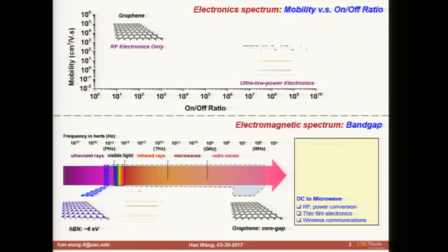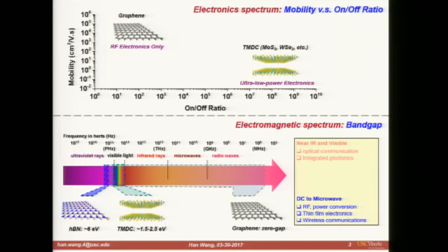In the past few years, we have also seen intense interest in the transition metal dichalcogenides family of 2D materials, with materials like molybdenum disulfide, tungsten diselenide. These materials typically have relatively lower mobility compared to materials like graphene, typically on the order of 50 to 100 centimeters square per volt second.